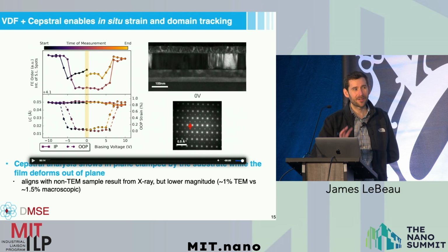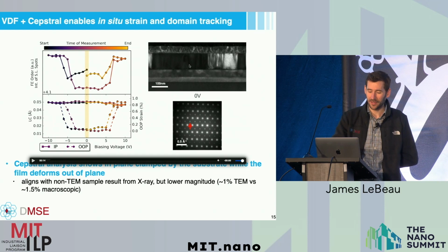That might not sound like a lot, but for anyone doing ferroelectrics, relaxor ferroelectric work, those are high strains in a very thin film. This is about 100 nanometers thick. And that aligns with ex situ measurements with XRD or other methods.